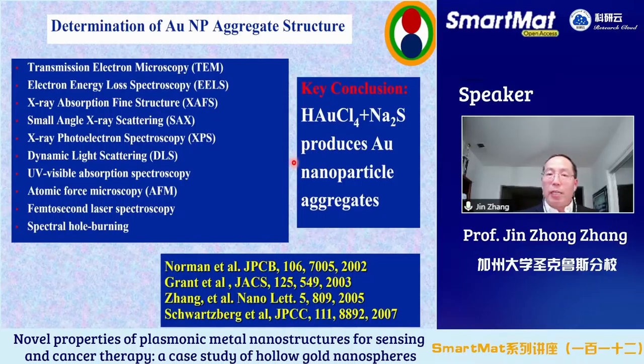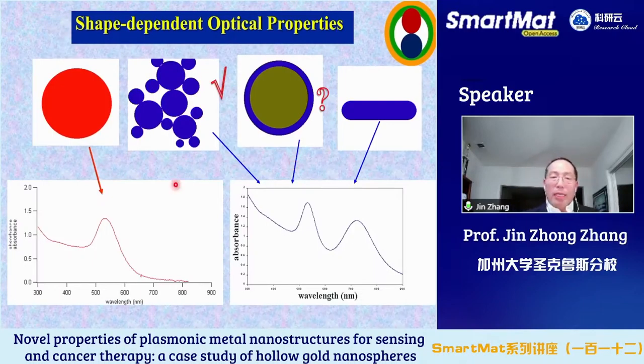So what is responsible for the two peaks? As I said, if you just have isolated gold nanoparticles, you will see one peak at 520, nothing else. Now we know we see two peaks, so it's not simply isolated gold nanoparticles. Well, first you thought, oh, might be nanorods. Let me grab a pen to show you. For nanorods, you have a longitudinal mode, if the polarization electrical field is along the long axis, or a transverse mode, if the electrical field is oscillating up and down or sideways, in the transverse direction. So you have two modes basically, transverse, degenerate, and longitudinal.